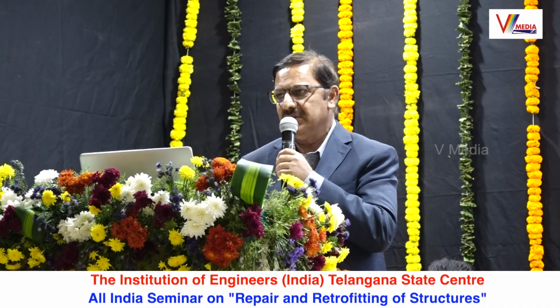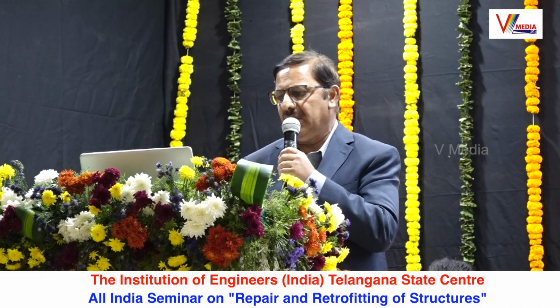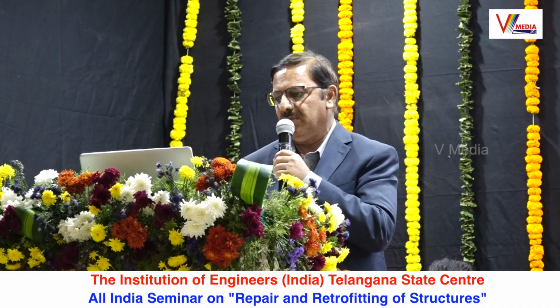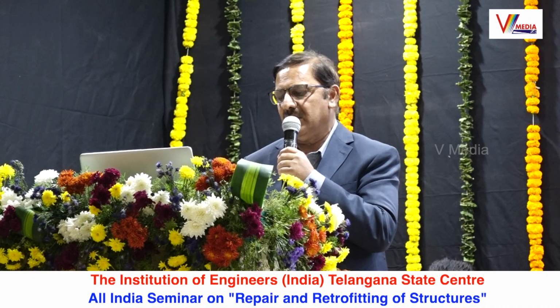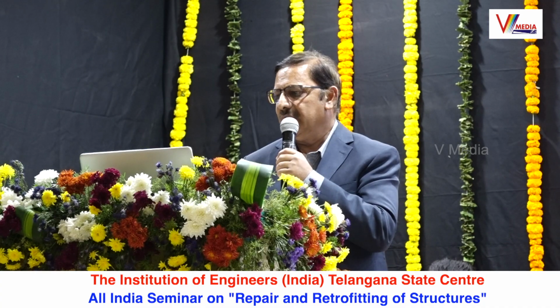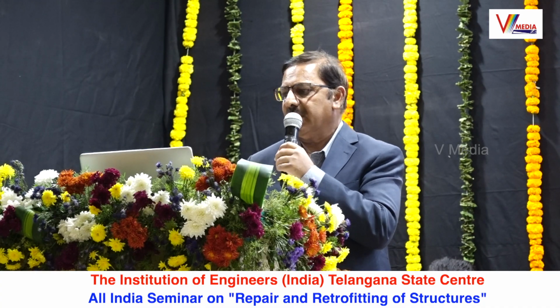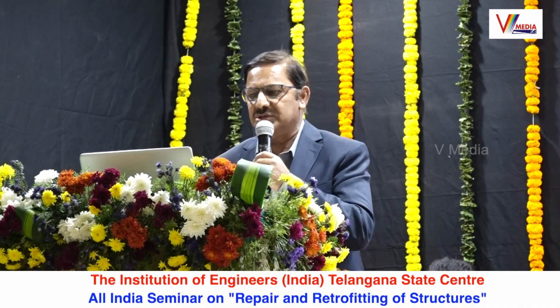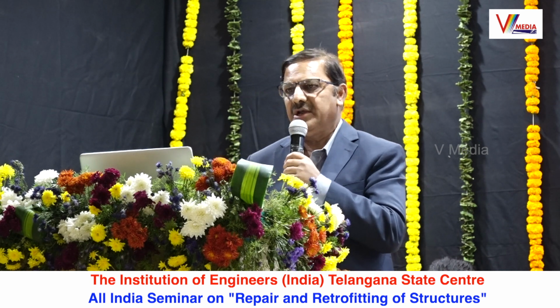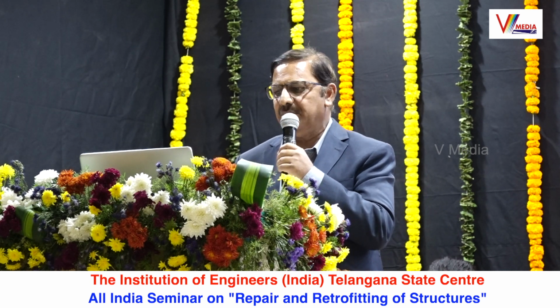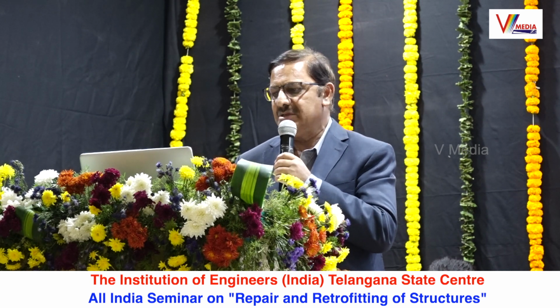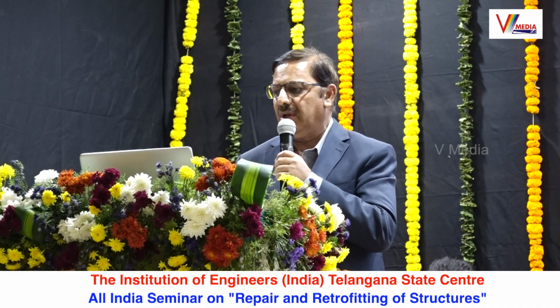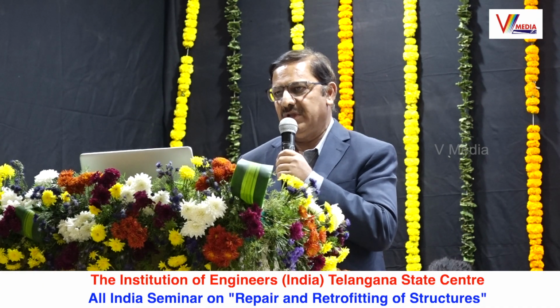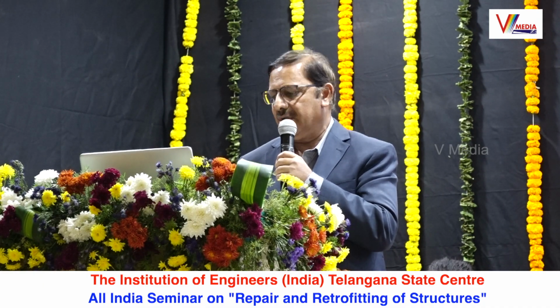Now when steel corrodes in concrete, in soil or water, anodes and cathodes are formed. Minus 500 is a cathode, and minus 600, as an example, is an anode. So the anode is corroding with respect to the cathode. How do we protect concrete structures against reinforcement corrosion? First is good quality concrete, which means a low water-cement ratio, use of supplementary cementing materials, good curing, a larger cover to the reinforcement, and good quality control practices.